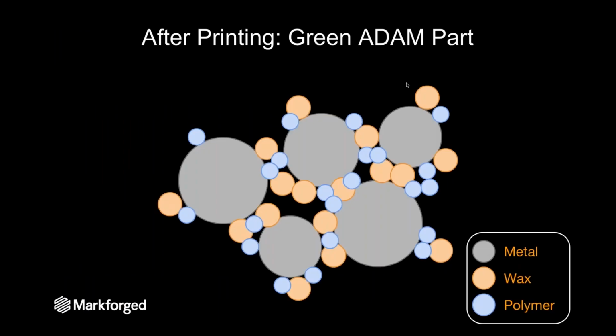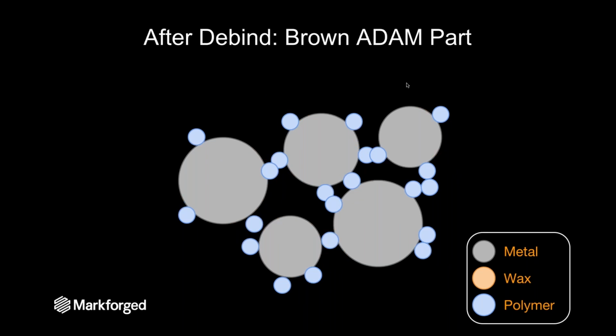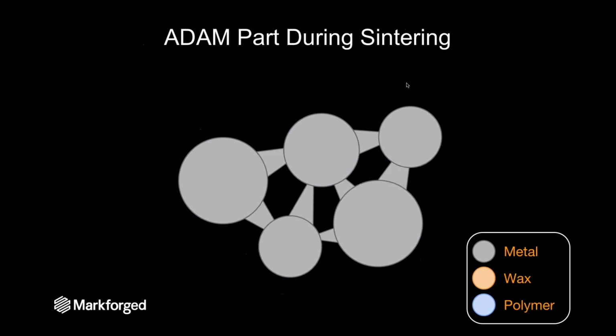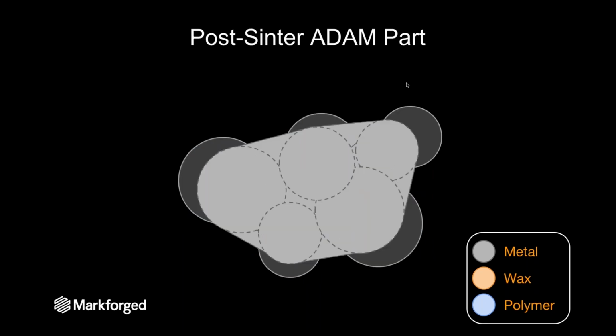I'm going to go into a more internal view of what's happening to our parts. As you print it, you have all of those wax and polymer binders that really hold the part together before you actually get to the sintering step. During our printing process, we don't melt any of the metal powder, so we don't get that hot. But we do melt the binders to help create the green part, as we call it. After the wash station, we have debound the wax portion of the binder. So we have the rest of the polymer holding it together until you can then put it into the sintering oven to start tacking those powder particles together, and then eventually getting your post-sintered dense part.